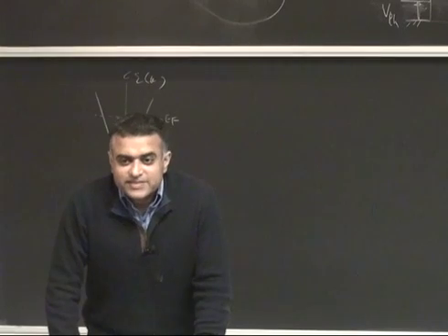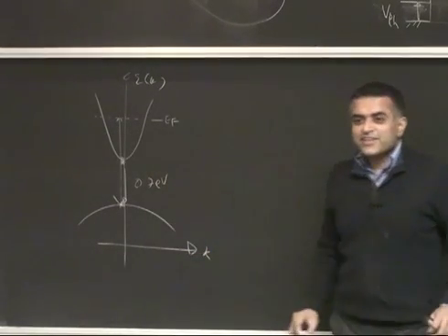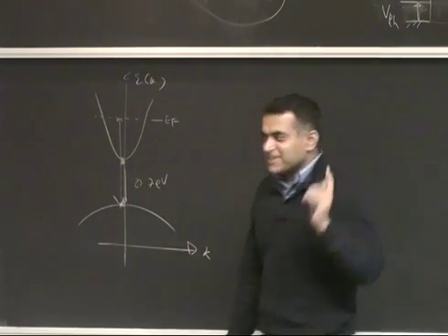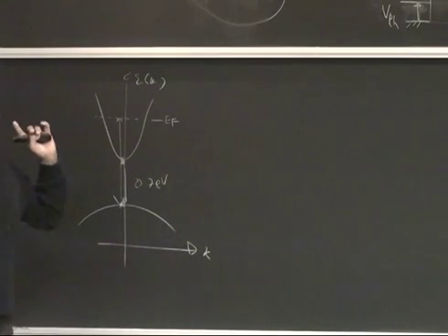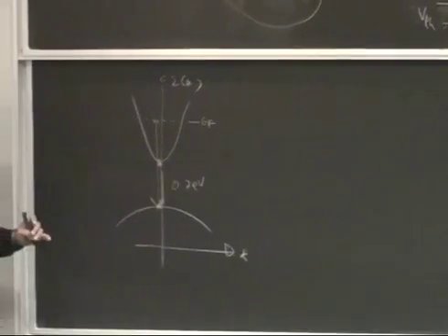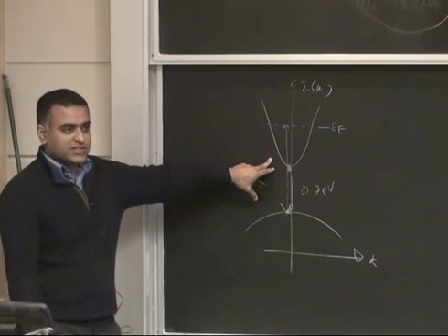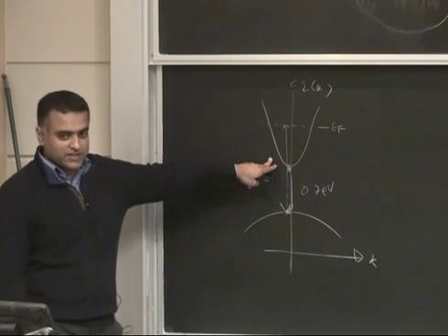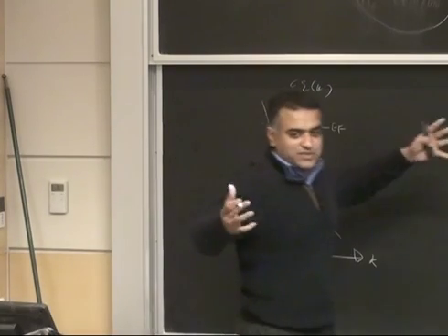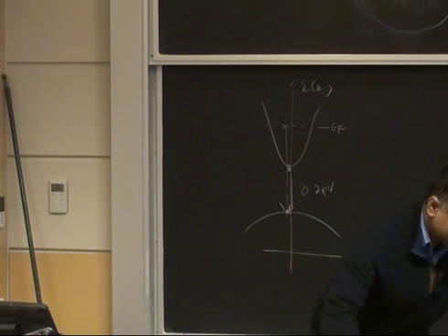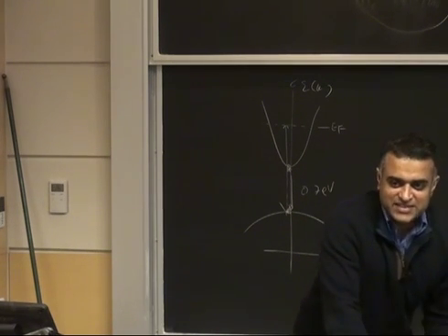I just have a quick question, haven't they done ab initio calculations on the band gap of...? Yes, they had. I will just tell you the truth, without any emotions. Till 2000, the ab initio calculations said that the band gap is 1.8 eV. And in 2003, they said it's 0.7 eV. So that's all I want to say. And it has been well accepted now. I'm not disparaging anything.